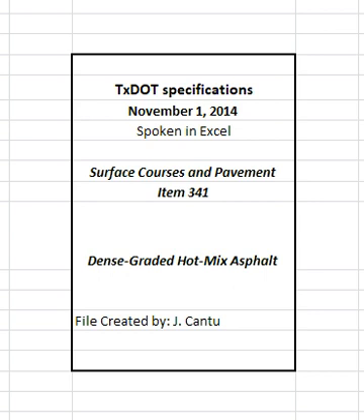Complete all compaction operations before the pavement temperature drops below 160 degrees Fahrenheit unless otherwise allowed. The engineer may allow compaction with a light finish roller operated in static mode for pavement temperatures below 160 degrees Fahrenheit. Allow the compacted pavement to cool to 160 degrees Fahrenheit or lower before opening to traffic unless otherwise directed. Sprinkle the finished mat with water or lime water, when directed, to expedite opening the roadway to traffic.